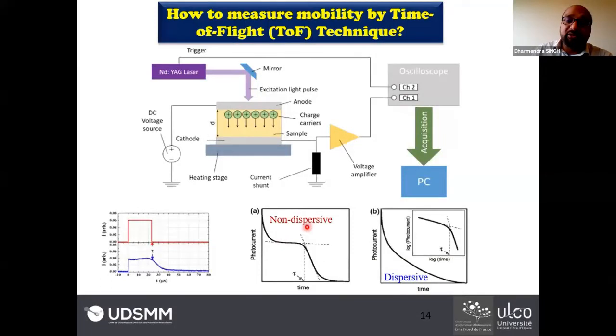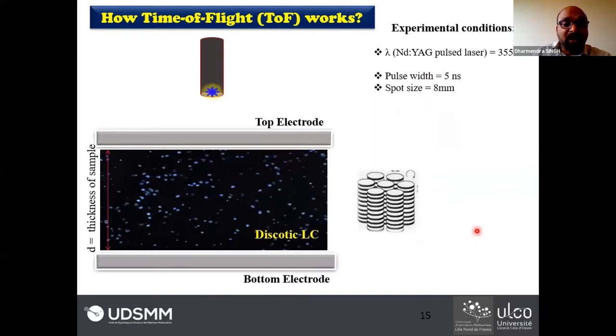But sometimes, depending on the material, if your molecule is heavy, or it is not completely absorbing the light, or if your charge carriers are trapped, you also get a dispersive curve. So in the linear scale, you are not able to estimate the transit time. Therefore, you are obliged to plot your photocurrent curve in the log-log scale, where you can estimate the transit time to estimate your charge carrier mobility. So here I would like to demonstrate how it works.